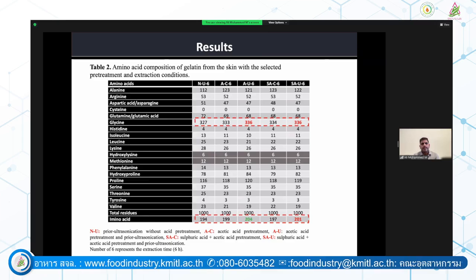Next, we saw the amino acid profile of these extracted gelatin molecules, and we found acetic acid had a higher content of amino acids, together with proline and hydroxyproline. These are unique amino acids present only in collagen and gelatin. And we saw the proportion of glycine is above 300. So for 1,000 residues, this proportion should be above 300. So we saw all the samples were extracted appropriately, and the amino acid content was higher.